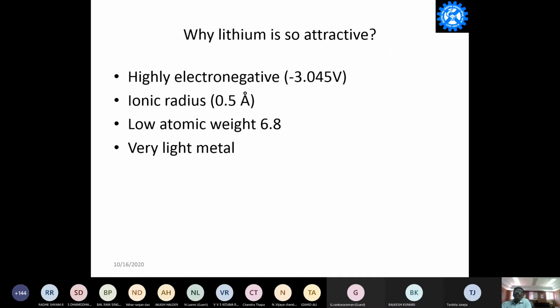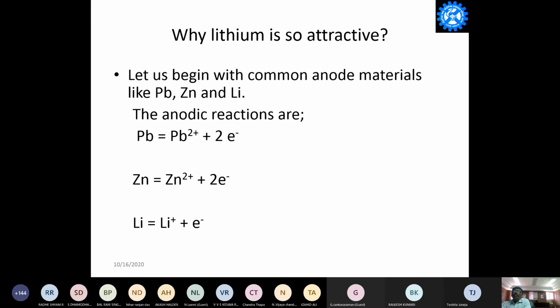So now I am coming to the third part, the lithium electrode and electrolyte poor interfacial properties, and how the lithium metal can be replaced. See, lithium is so attractive for lithium metal batteries because it is highly electronegative, its ionic radius is 0.5 angstrom, and it has low atomic weight and is a very light metal. But the problem is it has poor interfacial properties with the electrolyte.